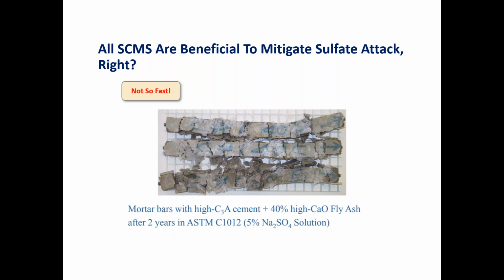So yeah, this is a two-year soak in sodium sulfate, and it's amazing how destructive the sodium sulfate was to that. And I would say that may be as bad, and potentially could have been even worse, than a version of that mortar bar made only with the cement and without the fly ash. So sometimes Class C fly ashes can actually increase problems of durability, not just not help. So next slide.